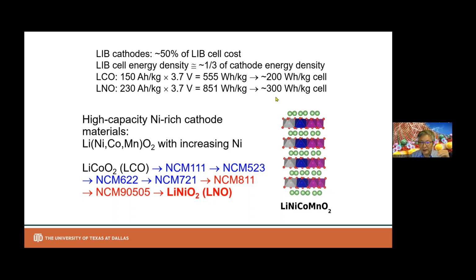so that as you increase the capacity of this battery for the same weight, of course, we want to use higher capacity, 50% more energy when you are using a cell phone. You want the same weight, same volume battery, but it has 50% more energy inside it. So that's what has been driving the whole lithium-ion battery chemistry, and that's dictated by the cathode material energy density because of the overall packing density of the battery cell itself. So that's the whole point.